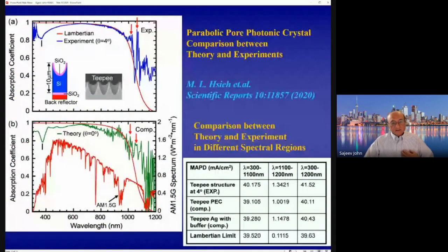We have some experimental confirmation of these effects, and these were experiments performed by my colleague Hsieh, who created the first of these parabolic pore structures. He's at Rensselaer Polytechnic Institute in New York. So here you see the structure that he made, a depiction of it. There's silicon in blue. Underneath that, there's a small buffer region of silicon dioxide, maybe about 100 nanometers in thickness. And this is the silicon dioxide anti-reflection coating that's placed on top of the silicon.